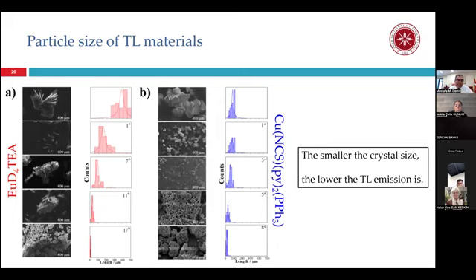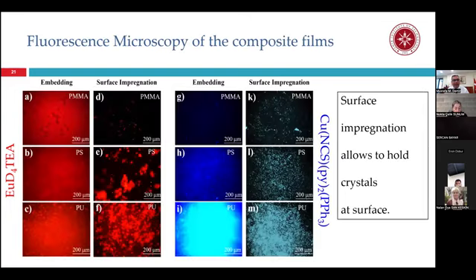In this slide, we see the size of crystals during application of mechanical force: initial, and the first, 7th, 11th, and 17th drop. You see the size distribution is getting smaller and smaller. As it gets small, we don't have enough triboluminescent signal, because when the particle size gets small, you have a lower number of breakages during mechanical force, and you obtain less triboluminescence signal. It is understandable. In this fluorescent microscope image, you see composites prepared by both embedding and surface impregnation.